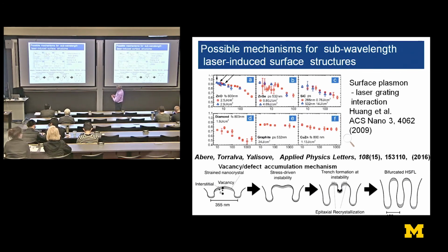And the surface plasmon can have the effect of coupling into that and causing, as you increase the number of pulses that the laser delivers to the structure. This is a log scale here, so this is starting to die here. So this is 10 pulses delivered, 100, and so on.